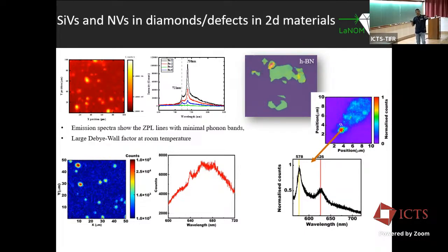We created defects by electron beam irradiation, and we created them very site-specifically, not randomly. We have control over where we want to create them, and we got a sample where we created them close to the edge, and we measured the PL spectra. You can see that it is a very nice zero phonon line compared to the diamond sample. This gives around a 50% Debye factor, which is a very interesting system, probably to replace diamond in future.